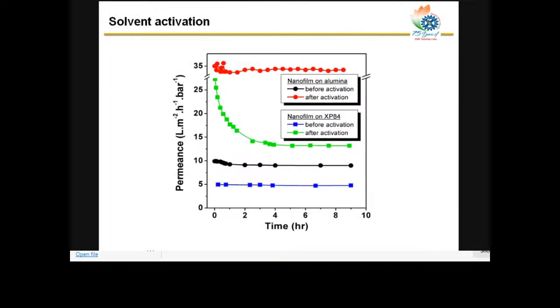Now, if we use DMF and apply it on top of the membrane, it is called activation. After solvent activation, we can increase the flux. The red data points on the top show we can get 35 liters per hour per meter square per bar, compared to a value of about 5 liters per hour per meter square per bar. So after solvent activation, we can make a different chemical structure and different density of the thin film. Depending on the activation, we can make a variety of polymer nanofilms with different separation properties.